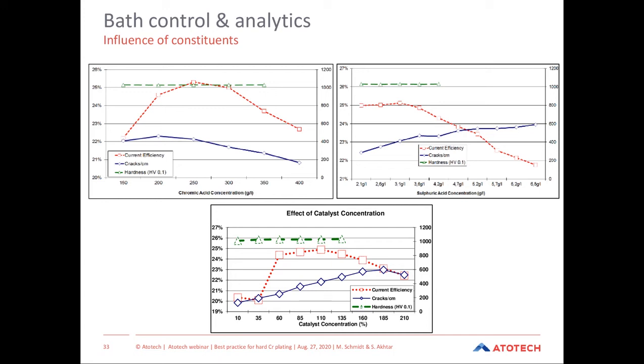Here you see the influence of the bath constituents on the performance of the layer or on the properties of the layer. Top left is chromic acid concentration. You see at chromic acid concentration of around 250 to 300 grams per liter, we have a maximum in current efficiency. And a drop of chromic acid, or an extensive increase of chromic acid, will result in a drop of plating speed and also a drop of microcrack count.